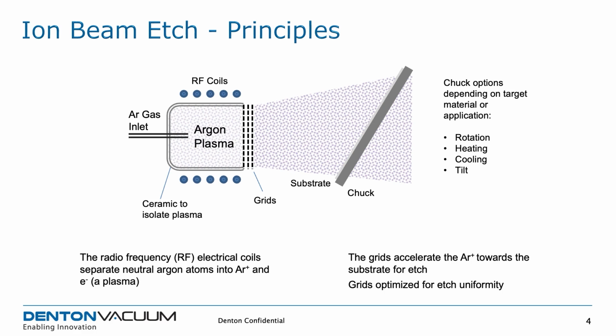So this beam is very broad. When it leaves the source, it's around 14 centimeter diameter, and it's a little bit wider by the time it reaches the substrate. And as I said earlier, the uniformity for that is about plus or minus 3% over 100 millimeters. But if you're looking at a single IC just in the center of the chuck, the uniformity is better than 0.1%.